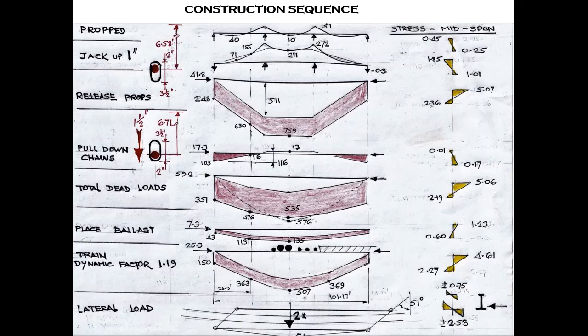They then tried to induce further pre-stress by pulling the chains down. And they hopefully still had some play in the vertical oval hole in the girders to do that, by pulling down with the bolt arrangement underneath the bottom flange. I reckon they wouldn't pull down more than 1.5 inches. You would have to have some sort of tolerance. If you pull down 1.5 inches, you only push the girder up by about 1/2 inch, simply because the cast iron girder is 65% of the stiffness. The chains only have 35%, so only 1/3 of it. So you don't get much out of that pre-stress, and you can see there the measly effect of pulling down the chains has only given a benefit of 13 tons-feet in several hundred.